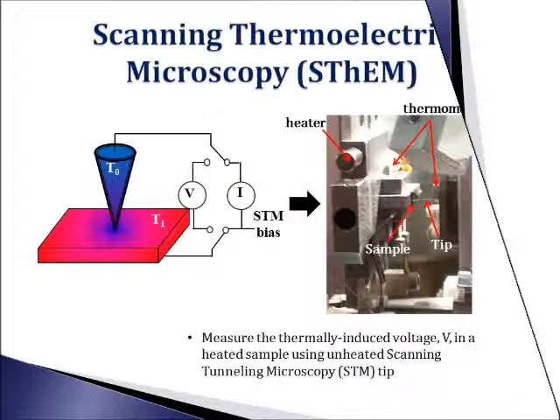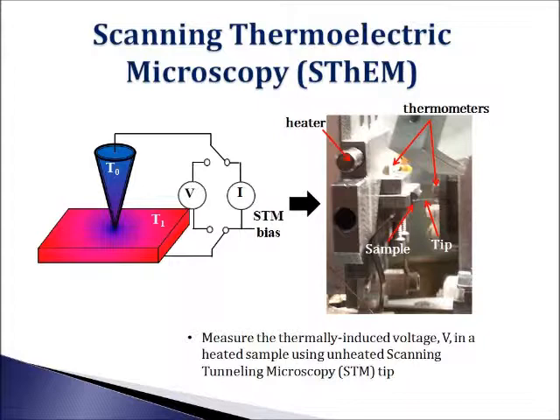In this work, we propose to reveal the mechanisms related to nanostructure using scanning thermoelectric microscopy to measure the Seebeck coefficient with nanometer resolution. In SThEM, an unheated scanning tunneling microscopy atomically sharp tip acts as a high-resolution voltmeter probe to measure the thermally induced local voltage V caused by a temperature gradient in a heated sample according to the Seebeck effect. This temperature gradient can be within a few to a few tens of nanometers. Therefore, this technique can probe the Seebeck effect with nanometer spatial resolution, which is suitable for studying the thermoelectric effect of nanostructured materials.